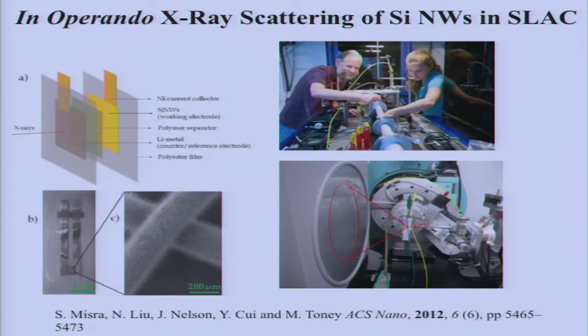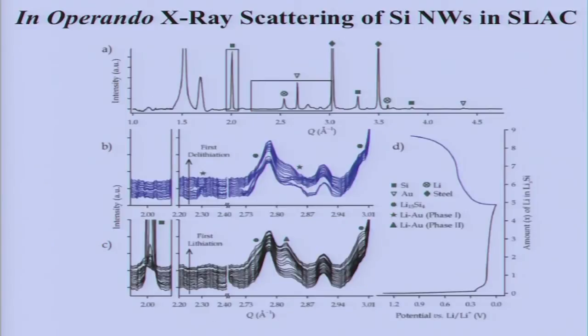We designed this structure with a mesh of stainless steel and grew these nanowires out. So when the X-ray comes in, we can look at just the edge right here, not really looking onto the stainless steel, but only these nanowires. This is a process, certainly too much data right there, but the conclusion is you can watch what's happening during charging and discharging, see the crystal structure change, see the new phase formation, and we use this to learn a lot about how silicon works.